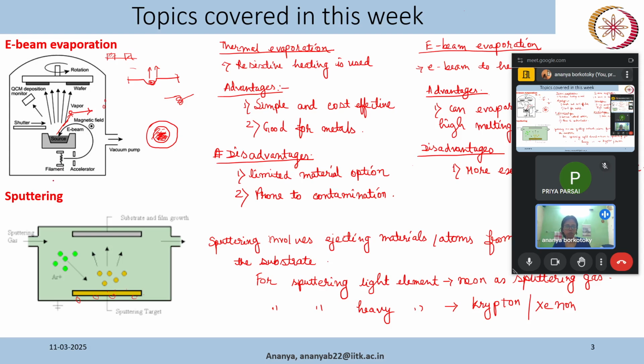Whereas in case of sputtering, we don't do the deposition at a very low pressure. Initially we maintain a very high vacuum so that everything is taken out and it's very clean inside the chamber, and then we do the deposition at a higher pressure. But for e-beam evaporation and thermal evaporation, we do the deposition itself at a very high vacuum or low pressure environment. Okay. And these are the advantages and disadvantages of thermal and e-beam evaporation. I will share the slide. You can go through it, and if there is any question, you can ask later as well. I hope this explanation is clear.